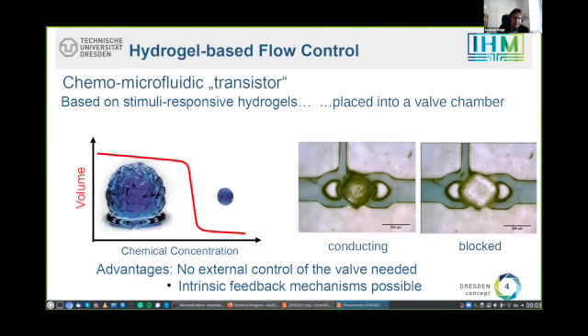Now I'm going to explain what hydrogel-based flow control is. That's a method developed in our group. And the basic component is the chemo microfluidic transistor. This microfluidic transistor is based on stimuli responsive hydrogels. On the left picture, you can see such a hydrogel, and the key idea is that the hydrogel size depends on the chemical concentration in the liquid. So if the chemical concentration is low in the liquid, the hydrogel will be swollen. And if we increase the chemical concentration in the liquid, the hydrogel will shrink. And this is a reversible process, so the hydrogel can shrink and swell again.